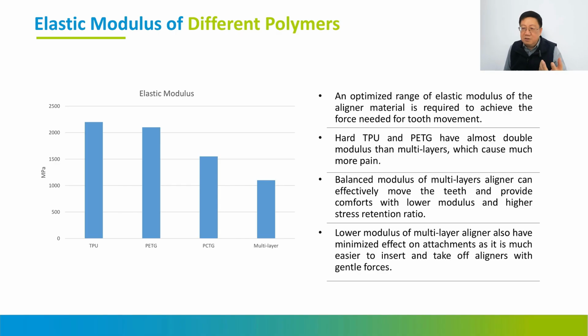So it doesn't mean you need a higher modulus on your aligner to move your teeth. It means, as I said earlier, continuous and more elastic modulus. How do we measure elastic properties? If you twist the aligner and it comes back faster, it rebounds faster, which means it moves your teeth faster. It's very easy for most of our users: they can twist the aligner to see how fast it comes back.